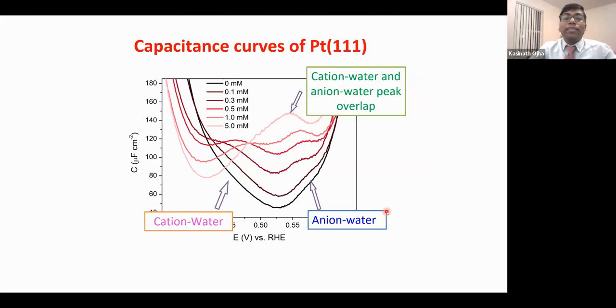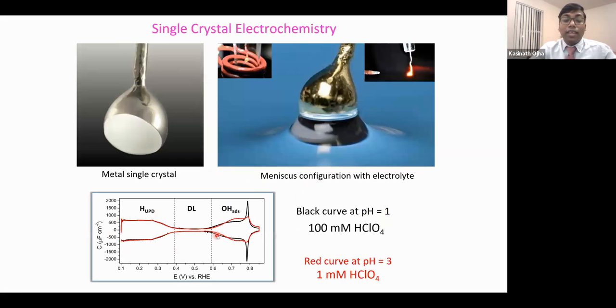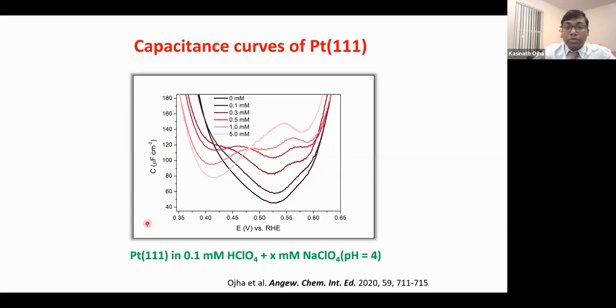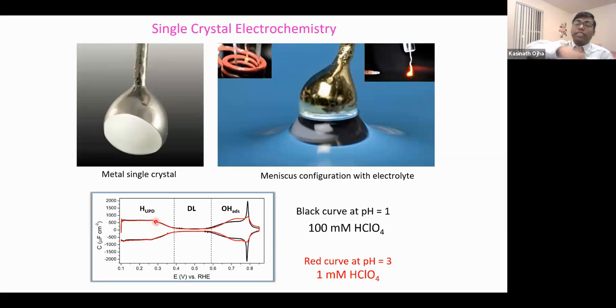No, we do calculate the surface area from the electrochemical signal. So you can calculate surface area from those adsorption areas. Basically, hydrogen adsorbs on each atom in the hydrogen adsorption region. If you calculate the total charge here, that will tell you how many hydrogens are adsorbed on the platinum surface. And from there, you can calculate how much area of your platinum is there. We call it electrochemical surface area. Electrochemically active surface. Okay. Yeah.